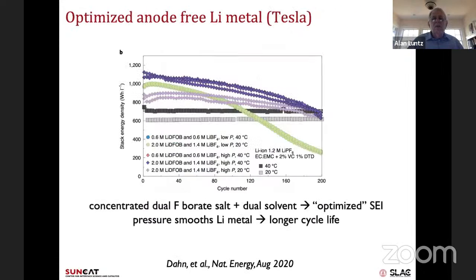So what is probably the best example of an anode-free battery in a liquid that I've seen was by a Tesla group. It just came out a few weeks ago. So I'll just share with you what it shows now. What they have is the black line, which is a conventional graphite anode lithium-ion battery, optimum state-of-the-art, and it will cycle thousands of times. So this is energy density versus cycle number, and it shows no change in that period. But when they made their optimum lithium metal battery in an electrolyte, they got quite a substantial increase in the energy density here. And it lasted 200 cycles or so. And that seems to be the state of the art.